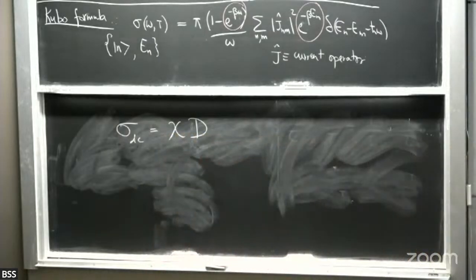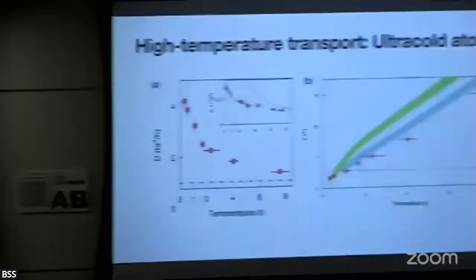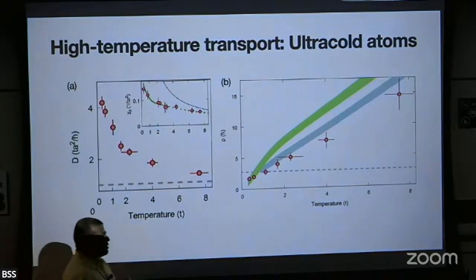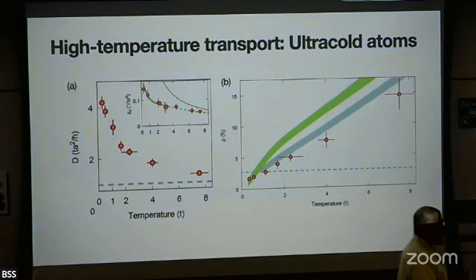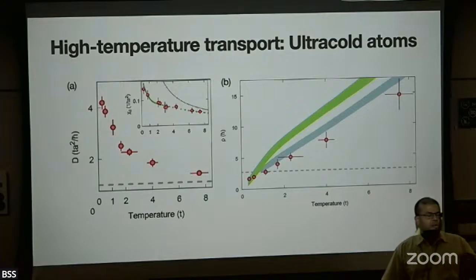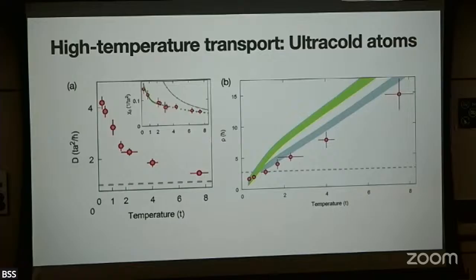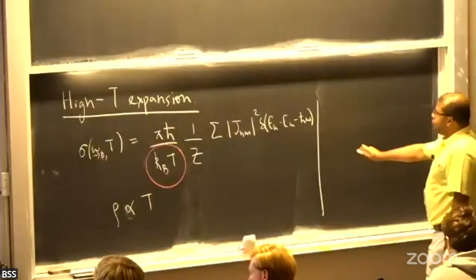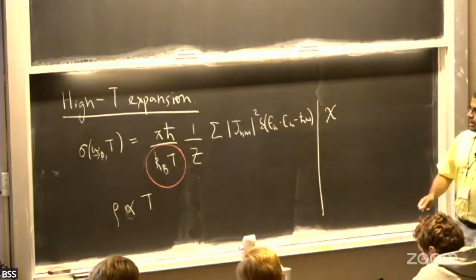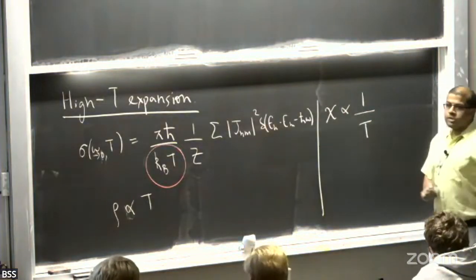Okay, so let's just first look at the resistivity. That's your region of T-linear resistivity. Actually, not quite, because there's something interesting going on. So it turns out this regime of T-linear resistivity is not coming out because of the scattering rate, which is what we started out by discussing, being linear in T. Okay? In fact, the scattering rate or the diffusivity is temperature independent. Instead, what is giving rise to the temperature dependence is coming from the compressibility. So again, how do you see that? So I'm going to leave that as an exercise as well. But again, within a high temperature expansion, if you calculate the thermodynamic charge compressibility, you can convince yourself that that goes as 1 over T.